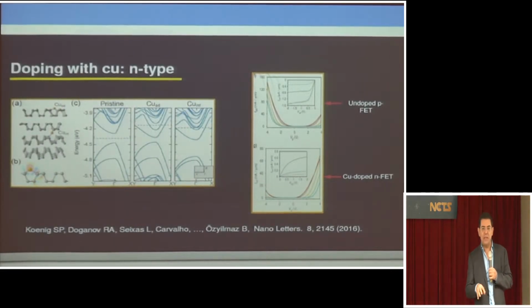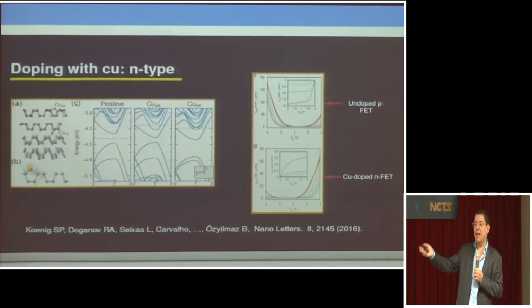Sometimes we want to do things intentionally. So in this case, we did an experimental study of copper. You put copper on top of black phosphorus and you look at what happens. So these are band structure calculations of copper atoms on phosphorene. And what we find is very interesting. Of course, copper is a metal. When you put it on top of a semiconductor, it dopes. It donates electrons to the semiconductor. But in this case, not only that, it affects the size of the gap.